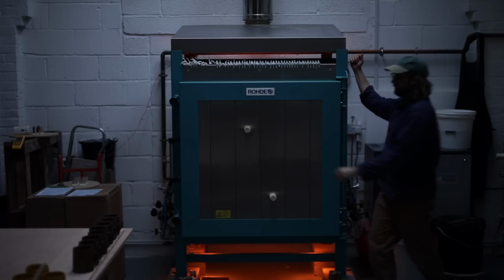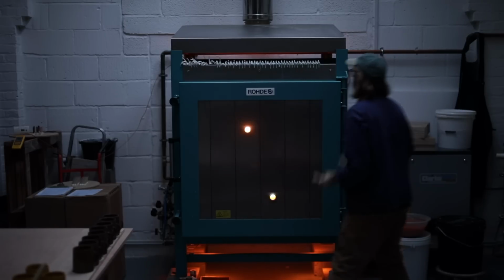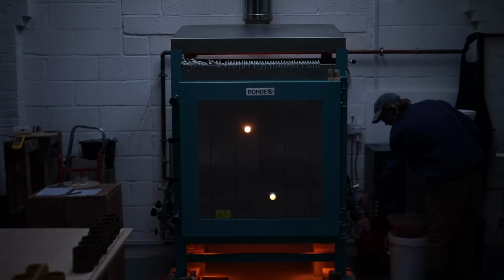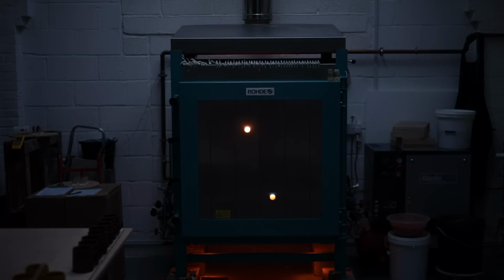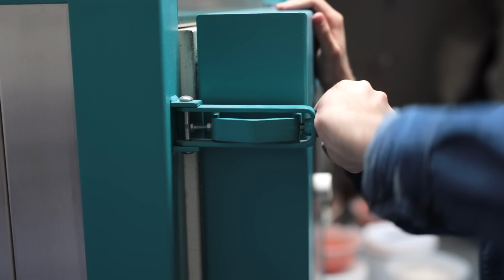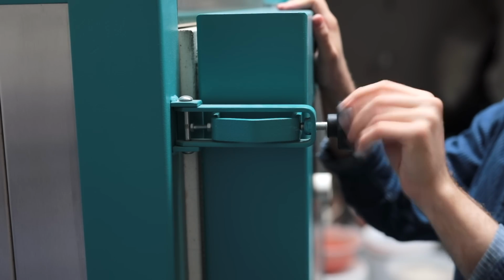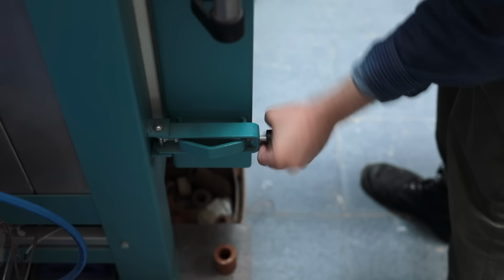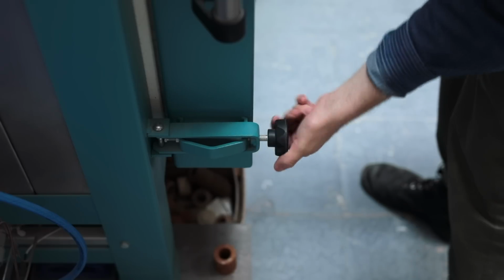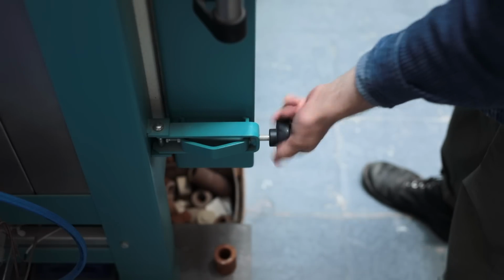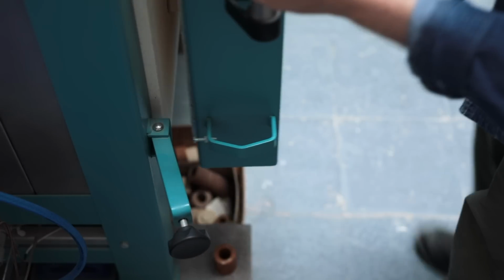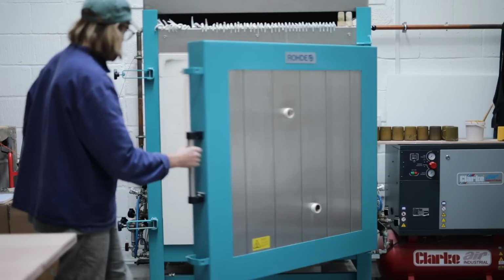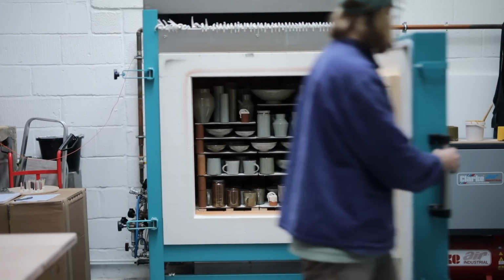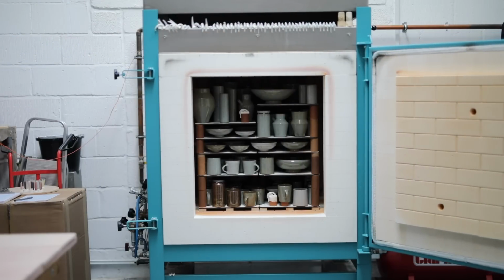I then fully open the dampers and the bungs in the spy holes and let the kiln crash cool to 1000 degrees Celsius. This helps to retain gloss and colour. 36 hours later and the kiln is at long last ready to be opened, which is always slightly, even after all these years, a relatively scary moment, as even though I know the firing went well and I followed my kiln firing charts accurately, everything has still been locked away in a chamber, and you haven't really been able to see it.